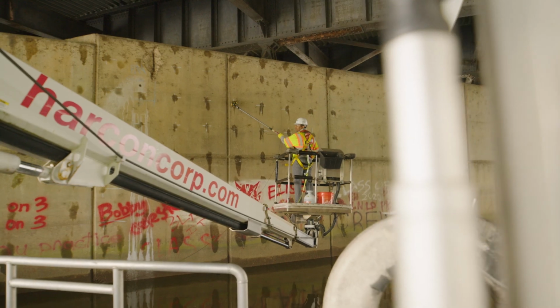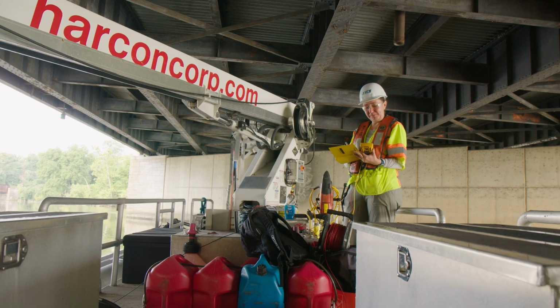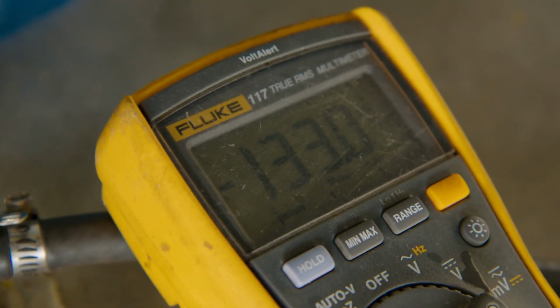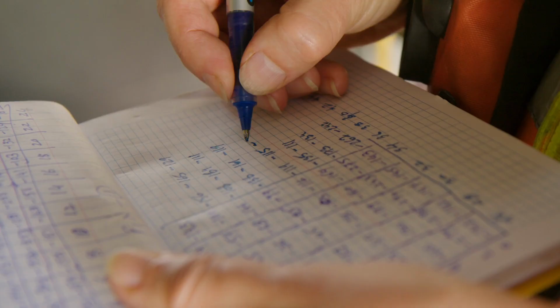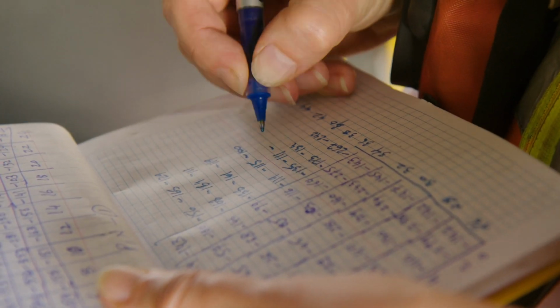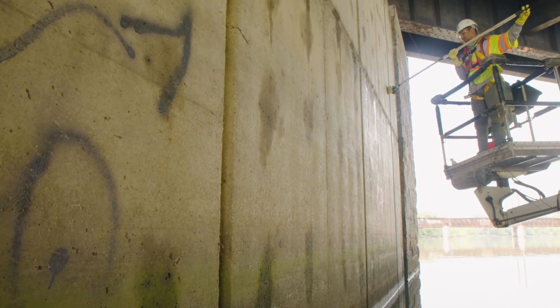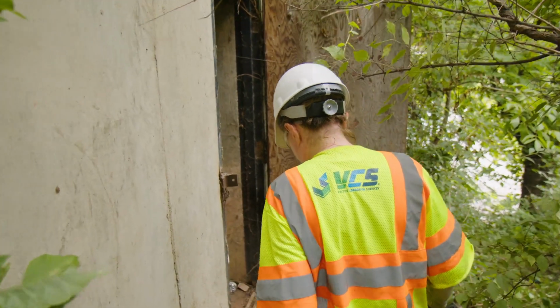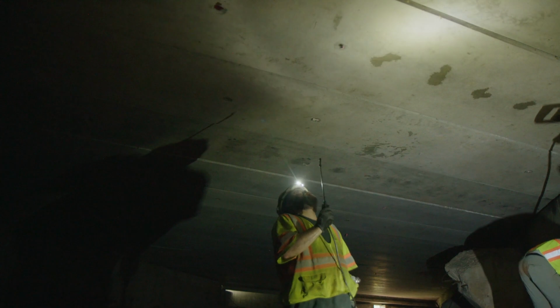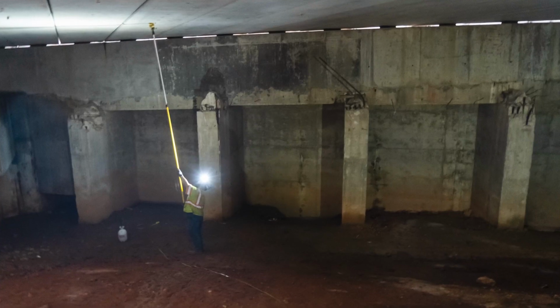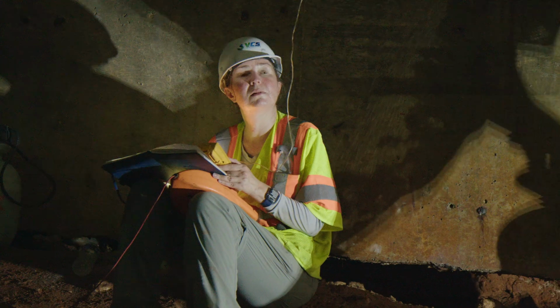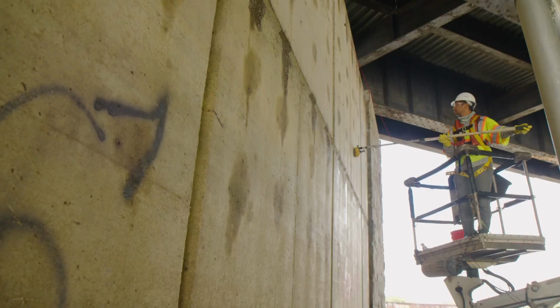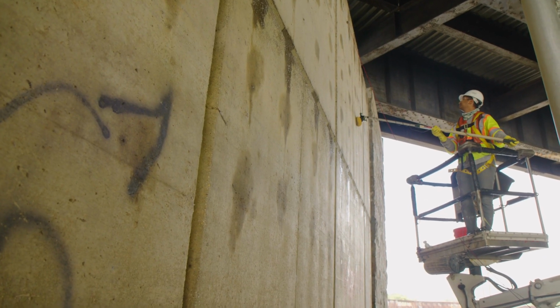The VCS team collected corrosion potential measurements on elements of the bridge, which included a pier, an abutment, and concrete girders. In the pier, corrosion activity was generally limited to the tidal region, which has the highest moisture exposure. Corrosion activity of the abutment was noticeable, showing signs of spalls and signs of moisture exposure due to expansion joints. The survey conducted on the girders determined them to be generally at low risk for active corrosion.